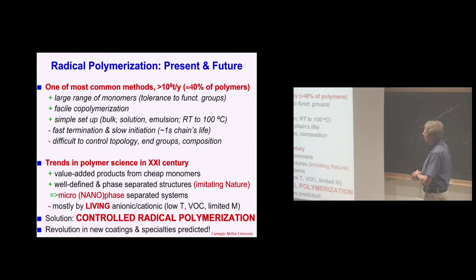Because you have a very large range of monomers. Practically any compound with a double bond can be either homopolymerized or copolymerized by radical means. And you have on the market maybe 500 different methacrylates, methyl groups, so to make plexiglass, but also hydroxyethyl substituent, it will be HEMA, making contact lenses, sometimes in combination with proteins, with nucleic acids, as you will see later, and so on. It's also very easy copolymerization. Reactivity ratios are close to unity, so you can make a myriad of different statistical copolymers plus block copolymers and some other complicated structures. But maybe industrially most important is that it is very simple to run them.